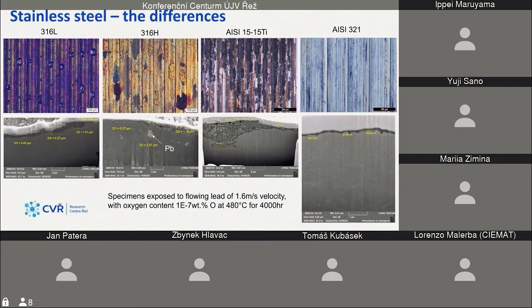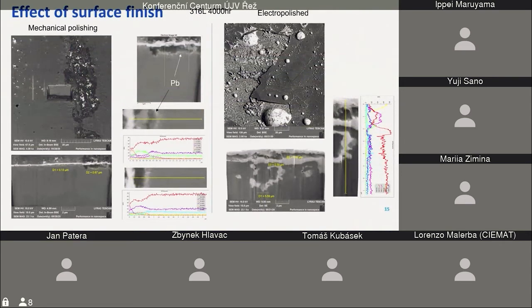What is very important is that there is no dissolution of nickel and penetration of lead. That was observed on 316H. That's the only steel that has such behavior in our test, and it's really hard to find an explanation for this behavior. So we tried to remove some machining deformation after fine turning by mechanical polishing and electropolishing to see what happens. And the result was quite interesting because the electropolished sample was attacked on grain boundaries by lead, which is not seen on the mechanical fine-turned specimens, for example. So the surface finish is definitely a thing that needs more study.